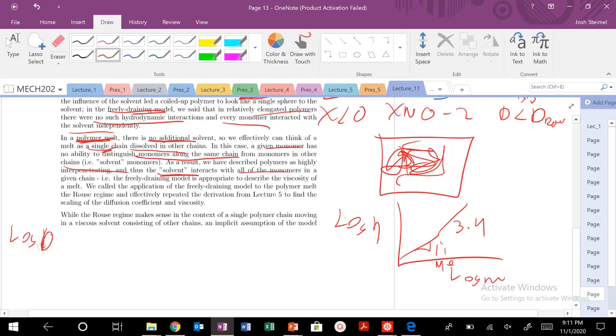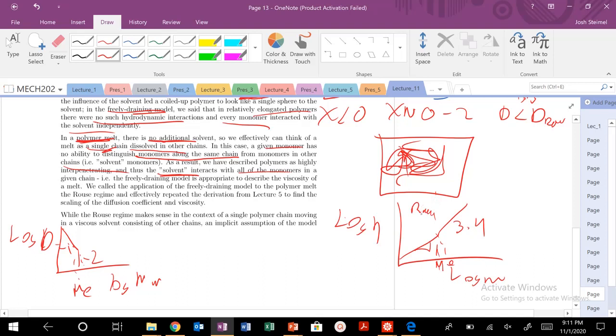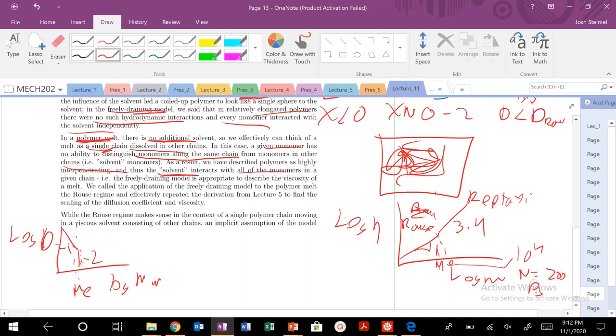This whole idea comes from the log viscosity vs. log molecular weight plot. We see two different scalings: a slope of one up until the critical molecular entanglement weight, and then it shifts to 3.4. And the same thing for diffusivity — you see a slope of minus one, and then minus two at this critical entanglement molecular weight. So when we're in the first regime, which we call Rouse — where molecular weight is really low — versus the reptation regime, that molecular weight can be as low as 10^4 to 10^5, which could be a pretty small number of repeat units. For polystyrene, it's about 200 repeat units.